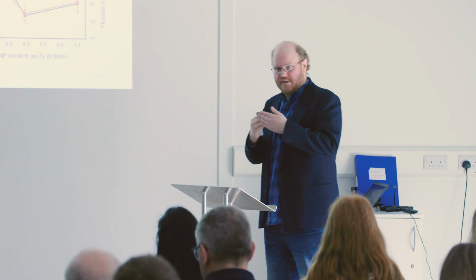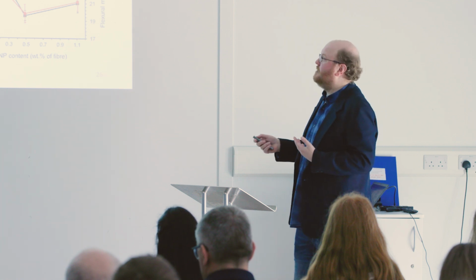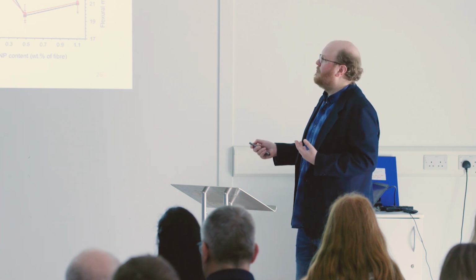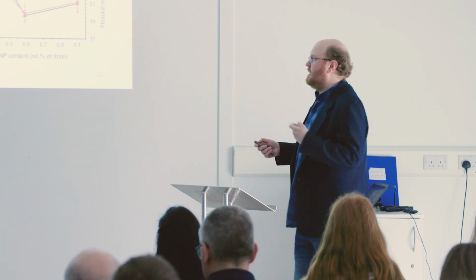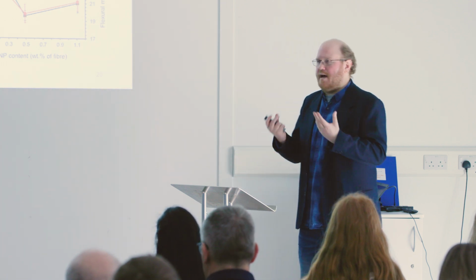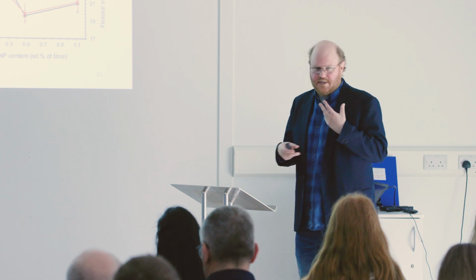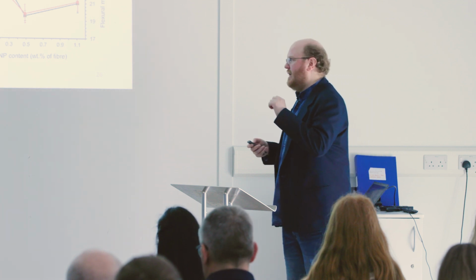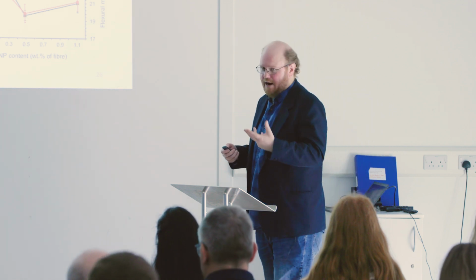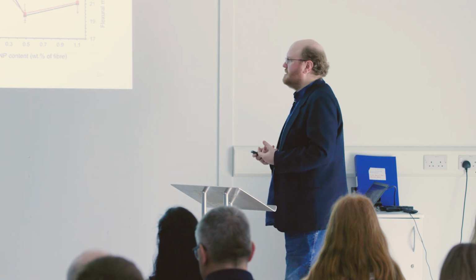You're basically introducing another interface that's going to fail when you're applying a mechanical load to it. So you want a little bit of material to give you benefits, but not too much that it starts to become detrimental. And that's generally what you'll find when you talk to companies or for any of this material that's being commercialized. It's about understanding just the right amount to give you the properties that you want.